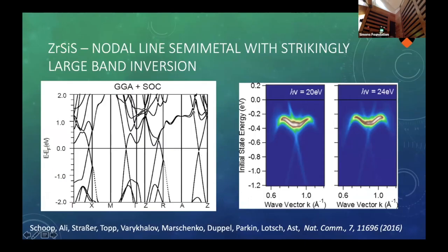What is remarkable about this band structure is that the energy range in which these bands are linearly dispersed is very large. Graphene, of course, has a larger range of linear dispersion, but most other real materials don't. These bands are crossing a bit more often in the Brillouin zone than in graphene. This is because it's a square net structure and not a honeycomb, and so this will result in a nodal line rather than direct point nodes in the Brillouin zone.